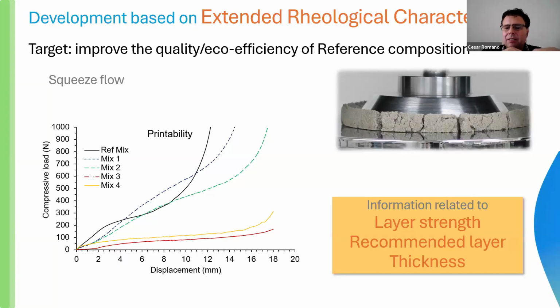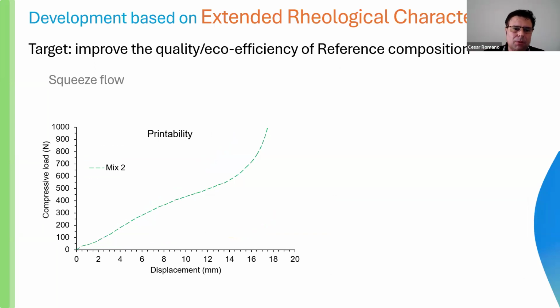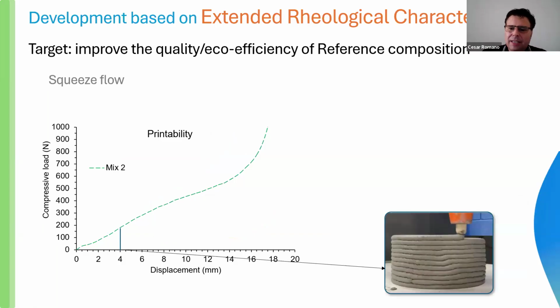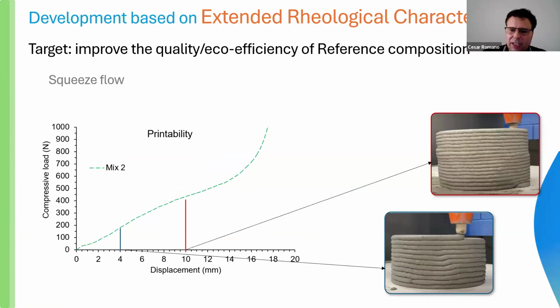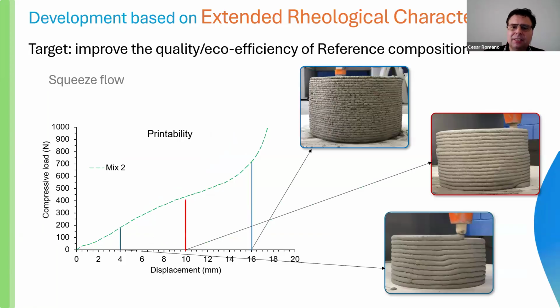We can understand the thickness of the layer we can press during the 3D printing process and things like that. For example, if we consider this mix 2, just for an example, we made the test of printability using this thickness of layer, this thickness of layer, and this thickness of layer of each layer. It's clear the differences in the quality of the materials.